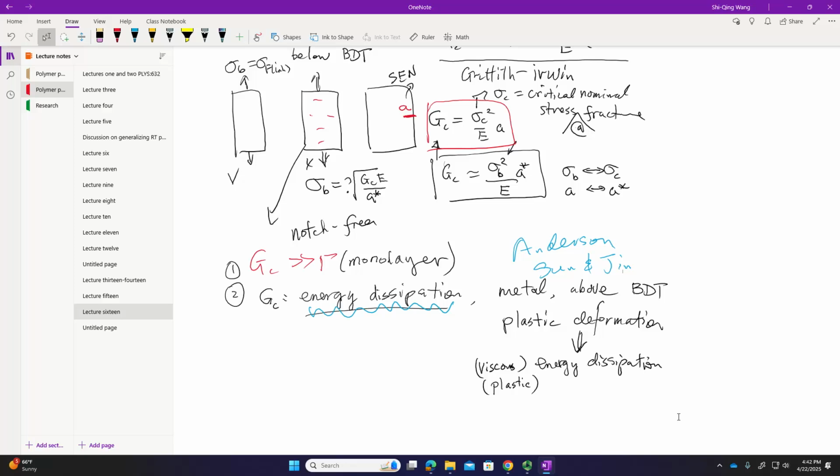I cannot do better. In fact, mathematically, we write GC as gamma plus the rest. The rest is largely plastic work, presumably, our view is, therefore dissipated. How convenient.